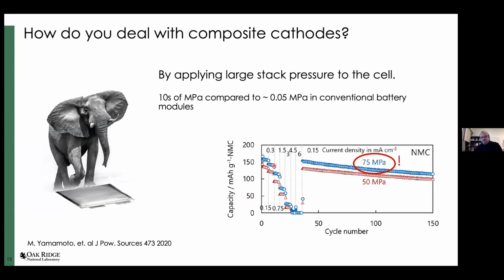So how do we deal with that right now in the lab? How do we deal with that separation along the interface? By applying tremendous pressures to the experimental cells in the lab, tens of megapascals. And if you compare that to a few kilopascals that you get in a normal battery pack inside the car, these are tremendous pressures. Again, as the example here is the beautiful cycling of the solid-state cell with LPS electrolyte, sulfide electrolyte, and NMC cathode. But look at the pressure applied here. This is a small experimental cell, of course, so they can afford that.